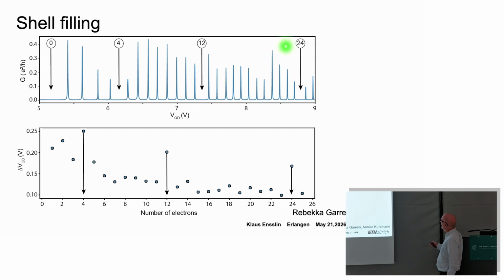Now let's look at this guy here. That's 12. So now we need some factor of 3 somewhere. Where does the factor of 3 come from? Now I showed you this Dirac cone, right? And this Dirac cone, we call it a cone because we think it's circular and symmetric, but it is not, right? In real life, in the real band structure, we need to satisfy this hexagonal geometry. So this cone, actually, as you go to higher energy, it starts having this underlying geometry of the hexagonal lattice. And we call that trigonal warping. So basically this cone is not just a circle, but it actually has a threefold geometry. And this is something that happens at very high energies, and usually you neglect that.